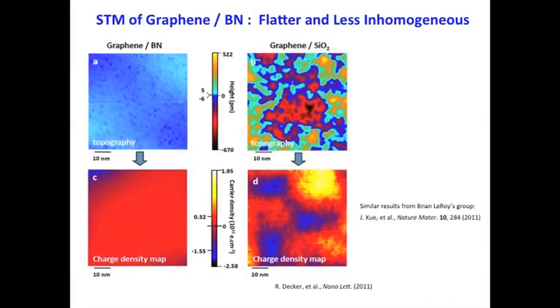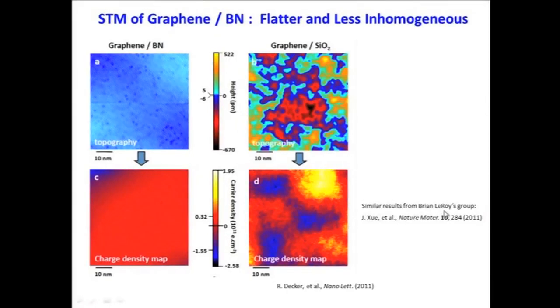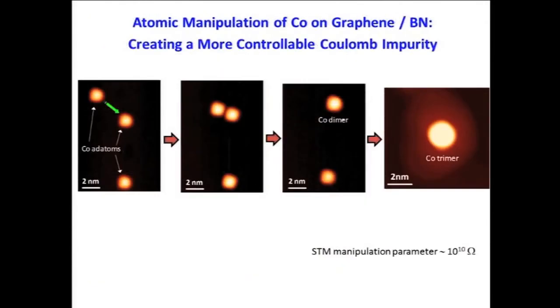I also want to point out that about the same time we were doing this work, Brian Leroy's group also did similar work in collaboration with the Columbia group, and they got results that are very similar to ours. So that's a great substrate to use, and now we're using graphene on boron nitride, and it allows us to solve another one of our problems. Because now that we have such a nice flat surface for the graphene to sit on, we can perform atomic manipulation on the atoms that we put on the graphene, and we can actually engineer our own defects by moving the atoms together. So we can create new defects that have different charging properties than the ones that we had before.